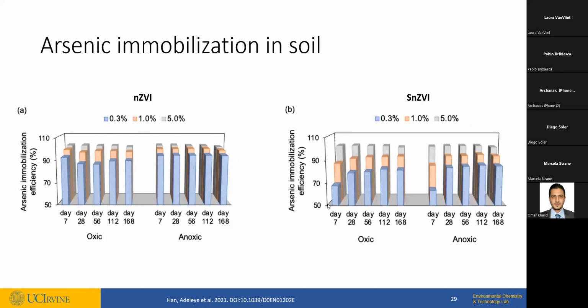So we continued that study for about 6 months, and clearly we don't see evidence of remobilization. In other words, the structure formed by the nanoparticles and the metals was stable. But again, this is without plants. This is just bare soil, and we were maintaining the water holding capacity of the soil throughout the study. In particular for SNZVI, we did see increase in the performance over time. And at the end of the day, the performance of SNZVI and NZVI wasn't really different, but NZVI had a higher immobilization kinetics.